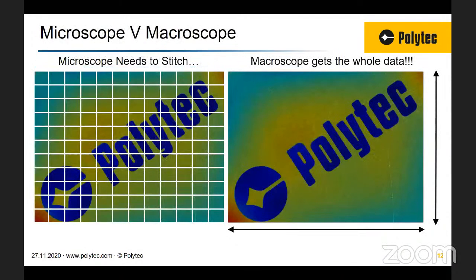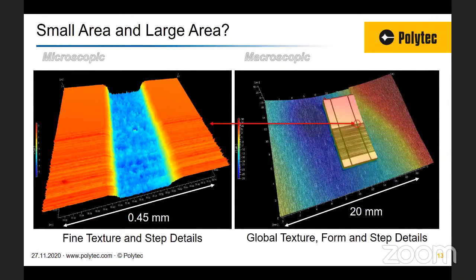With the microscope system, if you want to measure larger areas, you have to do image stitching. Whereas a macroscope gives you access to a different range of spatial frequencies. You simply see more of the surface. To further explain that, here on the left we have a microscope image, and you can see the very fine texture, the fine step height details, and all the details of the surface.